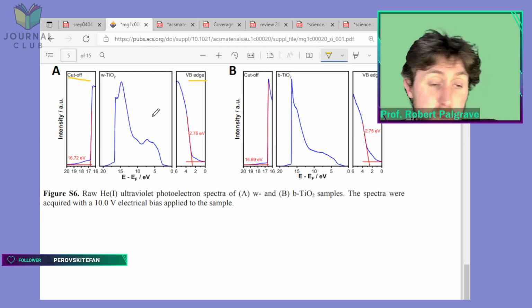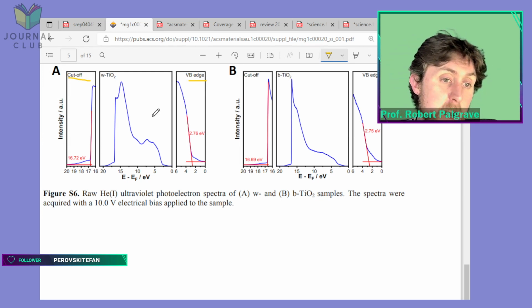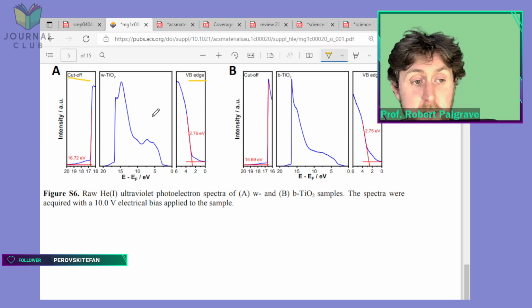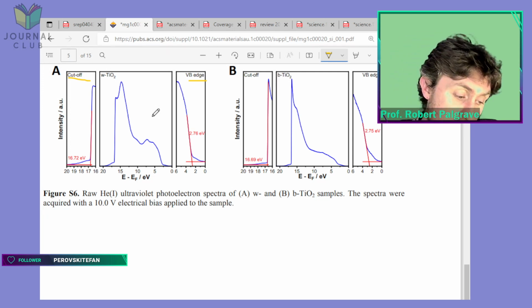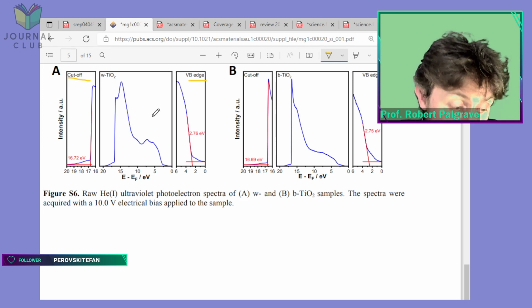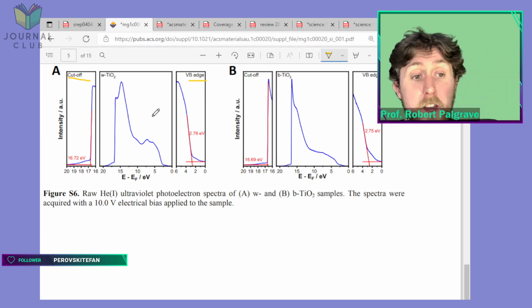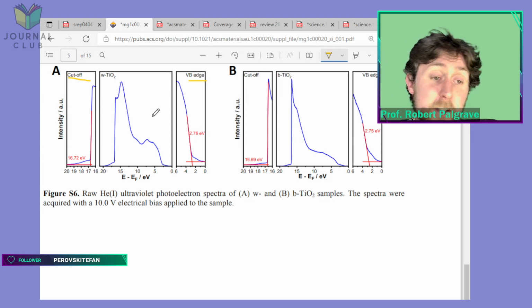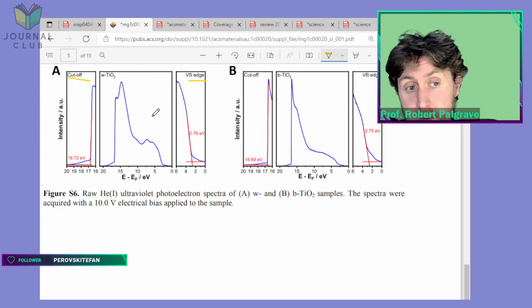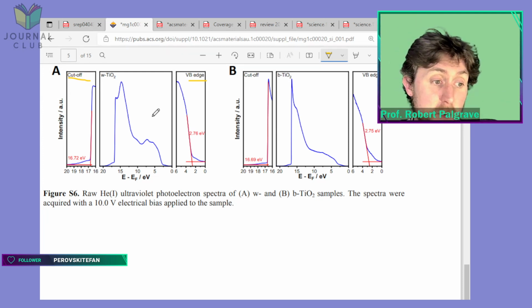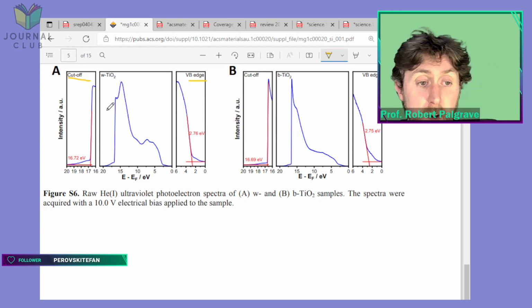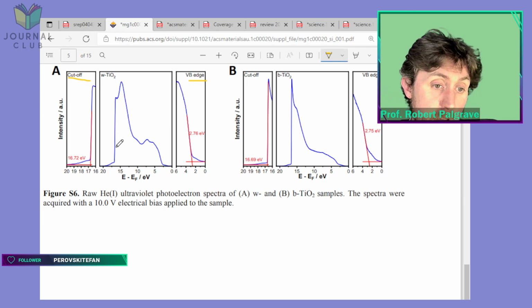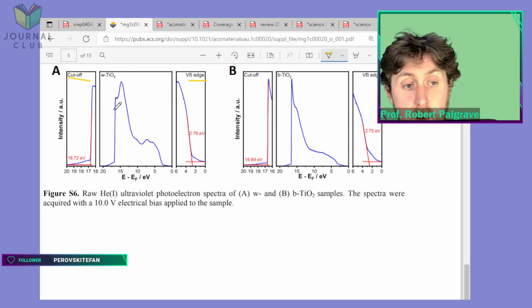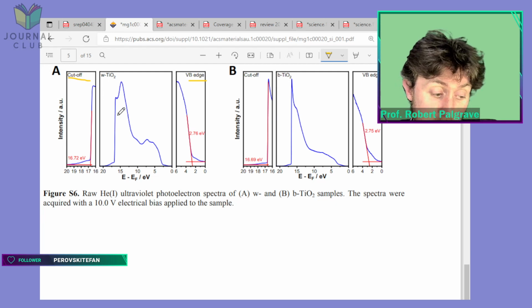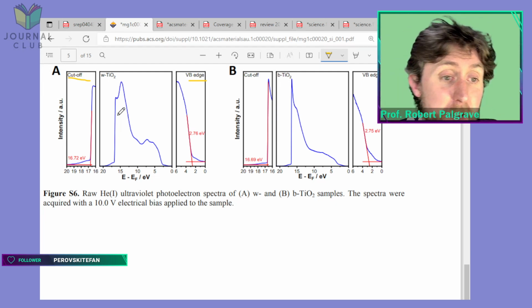What we have in UPS, especially helium-1 UPS, which is very low photon energy, is a lot of secondary electrons. Secondary electrons are electrons which are not ionized by the primary photon beam or by the ultraviolet photons coming in. They're ionized by some other energy loss processes. Some energetic electrons have been ionized by the photons, then those electrons bash into another electron which then gets knocked out of its atom. That second electron that comes out is a secondary electron. They come up with very, very low kinetic energy, but because the photon energy of UPS is very low, they appear in the UPS spectrum and they can actually dominate it.